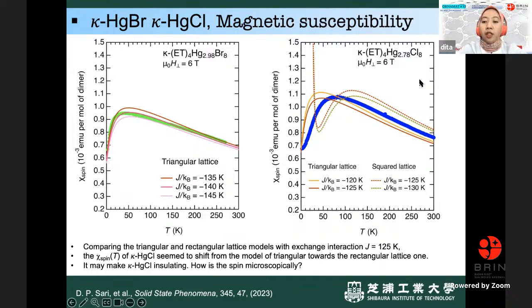But for the chlorine, it is a little bit in between triangular and square lattice. Maybe this is not perfectly the triangular lattice, so it's a little bit shifted to the square lattice. You can see this in the 120 Kelvin energy. So this is in between the triangular and square. Okay, so we confirm the triangular lattice of the bromine sample, I'm sorry.